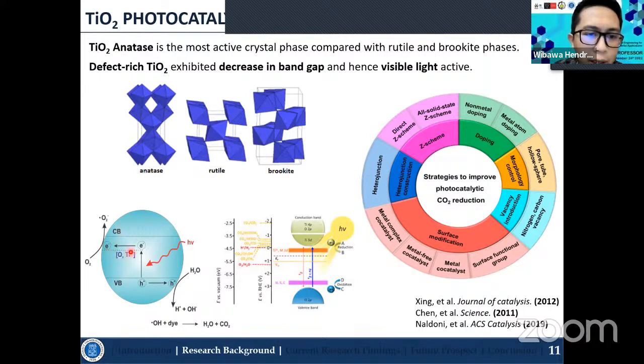One of the strategies to increase photocatalytic activity is creating defects. For instance, in TiO2 under stable conditions, the oxidation number of Ti is 4+. Here, we try to generate Ti3+ defects associated with the generation of oxygen vacancies. By creating these defects, we can lower the band gap of the photocatalyst. Lowering the band gap means the energy needed to activate the catalyst will be much lower, so it can be activated by visible light.